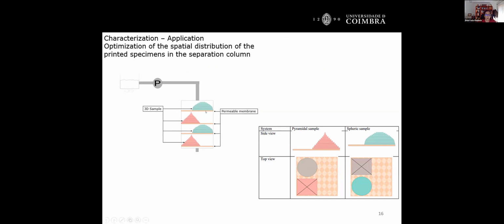And after having these preliminary tests, what we did was to make two schematic columns for making the test. So the first one, you have a column where you have the membranes and you have alternated spherical and pyramidal geometries, okay? And you have a peristaltic pump that is continuously making the water-oil suspension pass through the column. On another system, we had only the pyramidal samples in the column with some space for the liquid to pass besides the geometric shape, and we made another one with a spherical sample, okay?